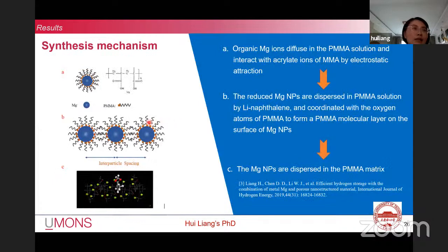Regarding those analysis results, we conclude the synthesis mechanism and model. First, the organic Mg ions are diffused into the PMMA solution and attracted to the acrylate ions of MMA by electrostatic attraction. And then the reduced Mg nanoparticles are dispersed in PMMA solution by lithium naphthalenide, the reducing agent, and coordinate the oxygen atoms of PMMA to form a PMMA molecular layer on the surface of Mg nanoparticles. Finally, the Mg nanoparticles are dispersed in the PMMA matrix.